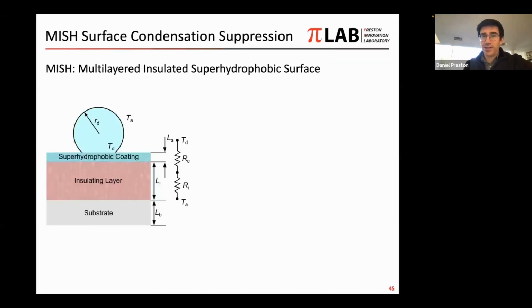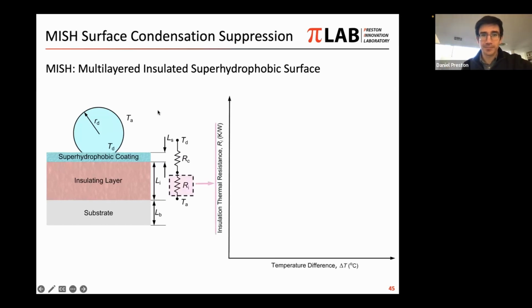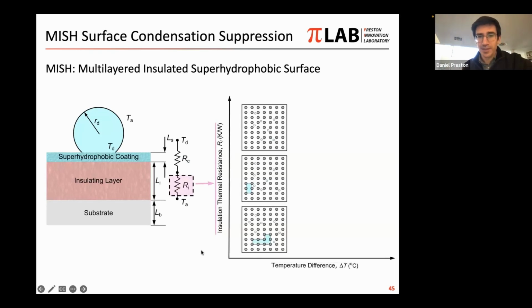The idea that I just described is shown schematically here. So we introduced not just the superhydrophobic coating, but also a thermally insulating barrier onto the substrate. And these are both spray-on processes. And the insulating layer has some thermal resistance that we can now tune. We can increase that as we'd like. And we might find in the left column that at low temperature differences, it doesn't really matter. All the performance looks essentially the same because we get very little evaporation and recondensation within the structures.